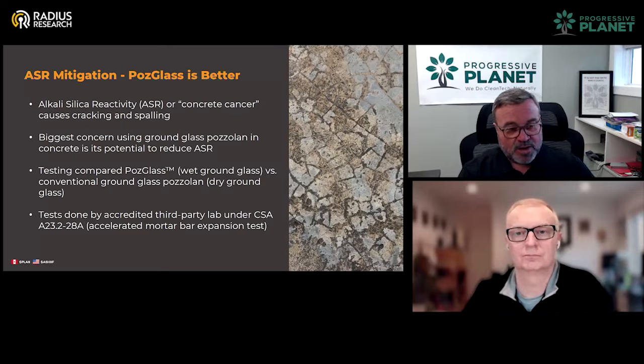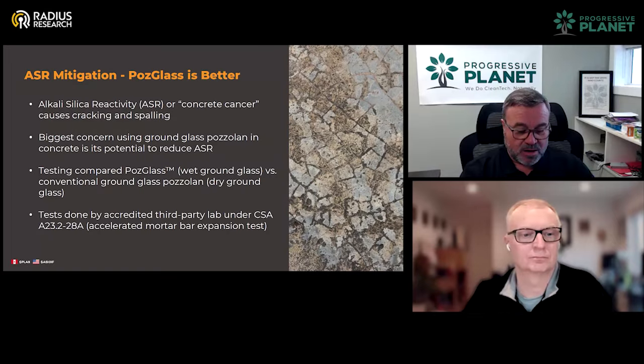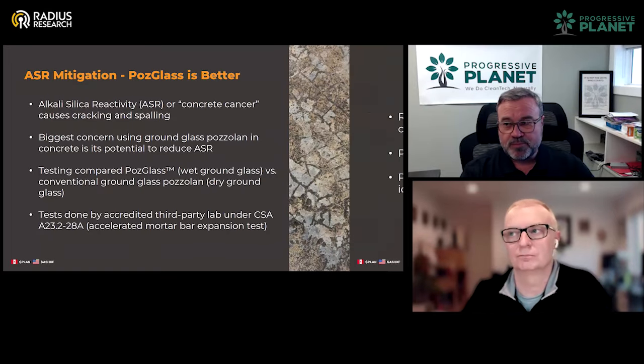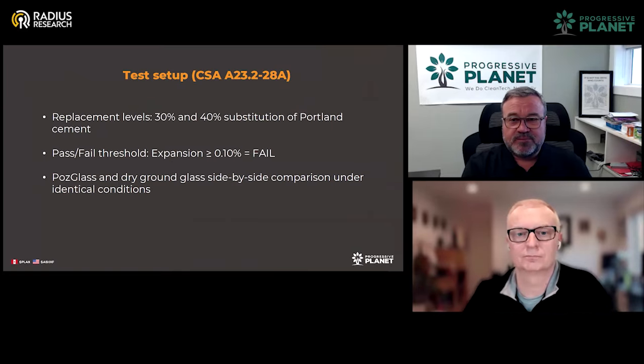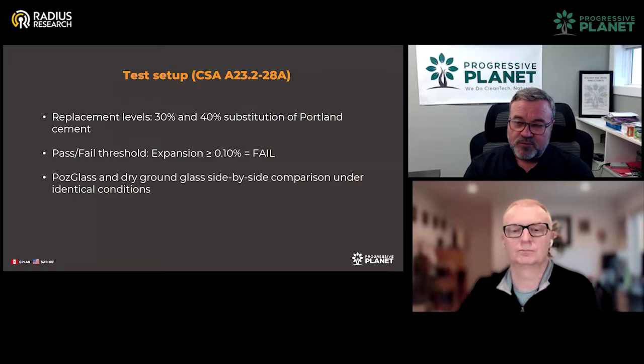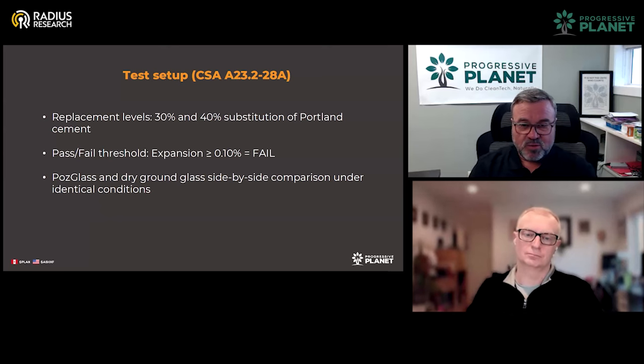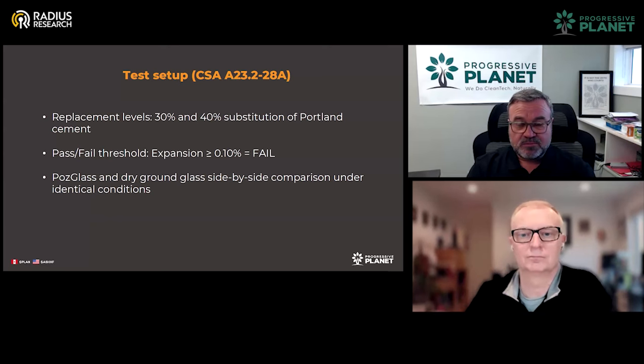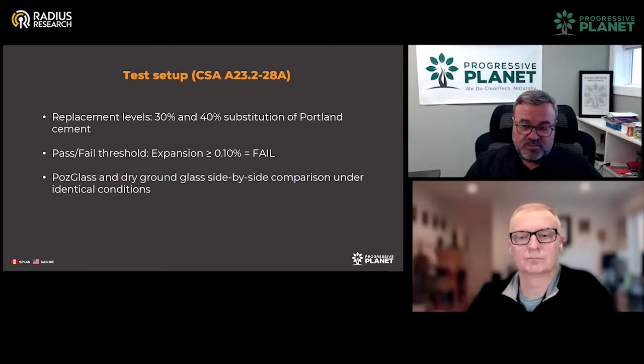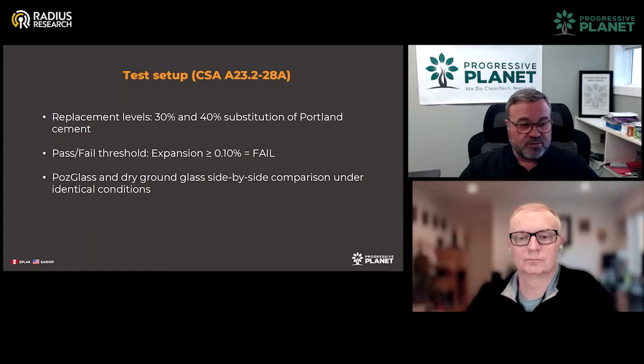What you do not want to see is expansion of the cement mortar bar. The more it expands, the more there is presence of ASR in the mix that you're testing. In the test setup, we replaced 30% and 40% of Portland cement in these mortar bars with both PozGlass and traditional ground glass pozzolan that was dry ground. Everything else, the particle size, was exactly the same. The only variation was that we tested PozGlass versus traditional ground glass pozzolan.